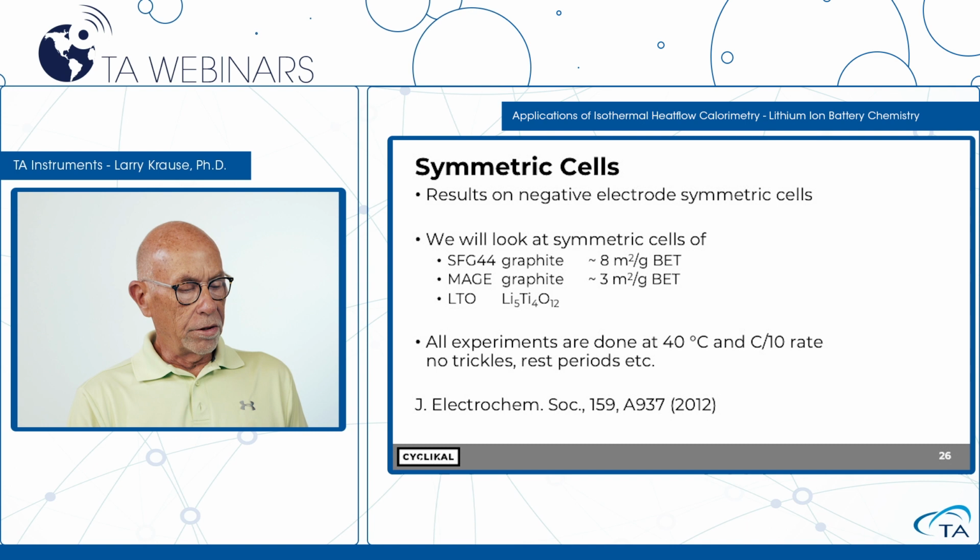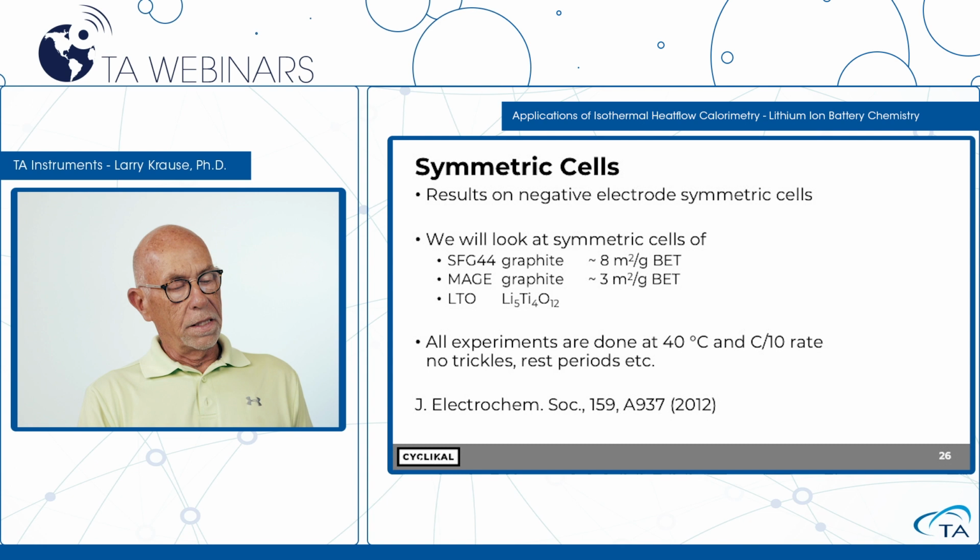And then a third electrode, which is the titanate, Li4Ti5O12. Now, this is a very interesting electrode. Lithium-ion batteries made with this negative electrode compared to graphite are far more stable than the graphite electrodes. I've seen examples, so these will cycle 10,000 times without any capacity loss. They're very stable. Very stable batteries.